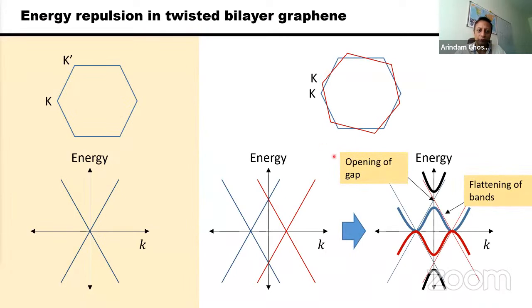Now, if you look at the energy bands, a very easy way to understand the new bands is as if they have been repelled or flattened because the two graphene layers are interacting with each other. That means, for example, this is the original old bands. And you can see when the two graphene layers, the blue and the red ones, start interacting, the new bands are essentially formed, which are flatter than the old bands. And this flatness is very important because when you make the electronic energy bands flatter, the density of states increases, and that leads to new physics, strong correlation physics. And that's what we have been interested in. Many of the phenomena connected to this twisted bilayer graphene are connected to strong Coulomb interaction that comes from this flattening of the band.